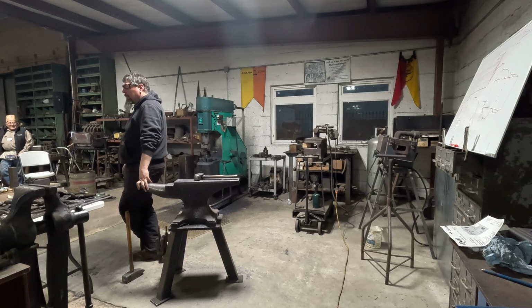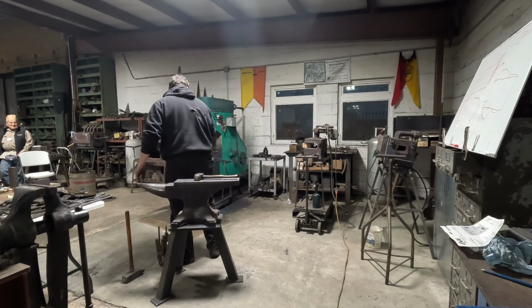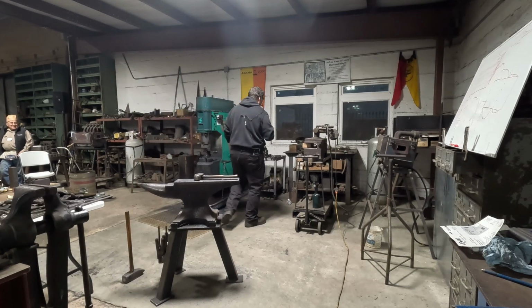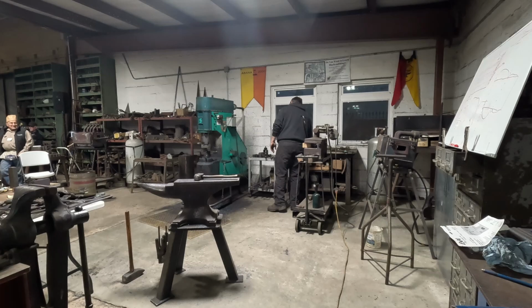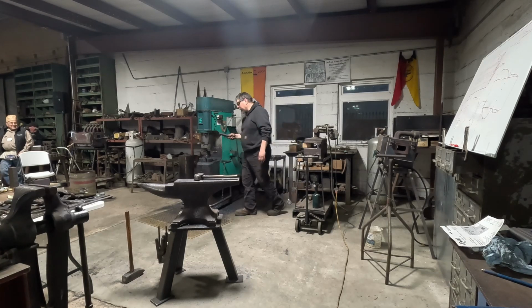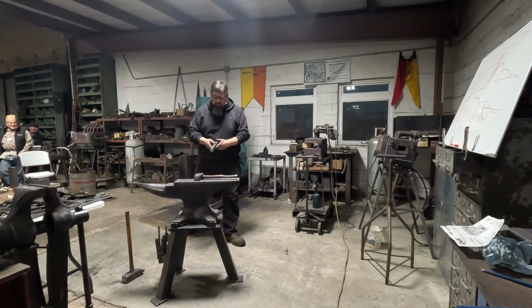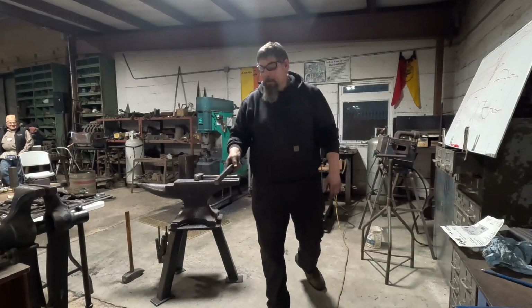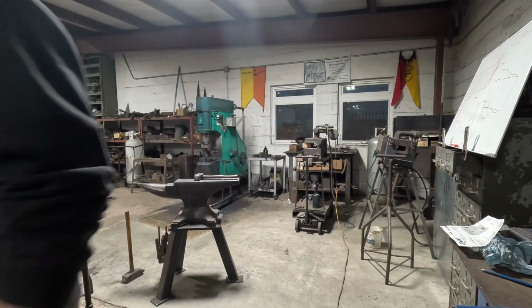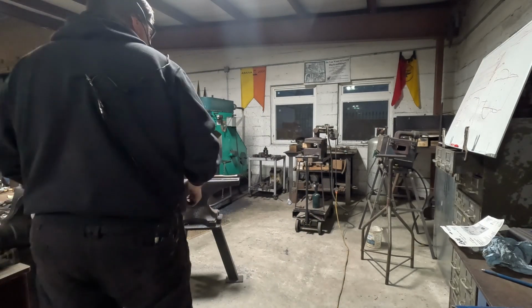I don't think that the presence of the copper in the forge by itself is the problem, but copper in contact with your metal will definitely cause an issue. And I have another show and tell piece that we can pass around. This is not a problem from copper, but copper contamination would look very similar to what you see here. So there's an interesting story there.